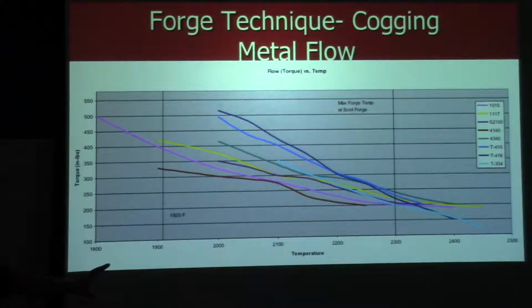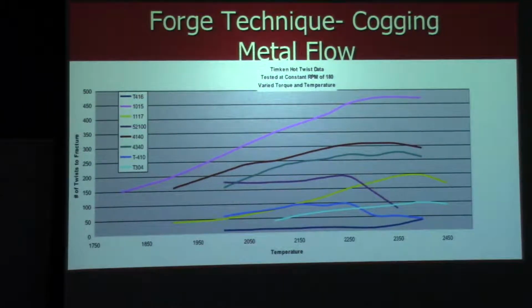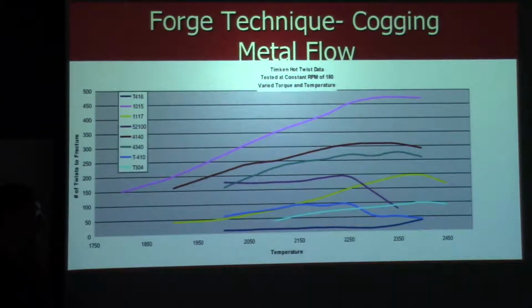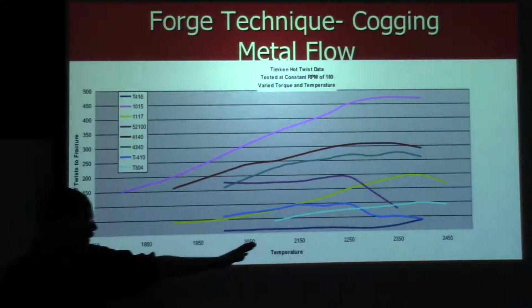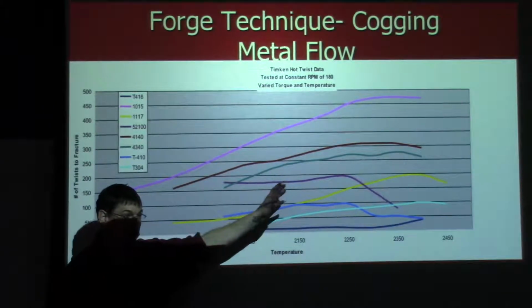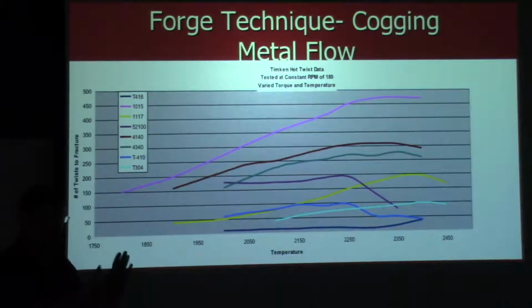Okay, so this is our graph of temperature versus flow stress, or torque as it's presented here. Any other questions? Any other answers to my questions? All right, so we're going to show another graph. This is the other parameter measured from this test, which is the number of twists to failure. It's the same exact situation. Pick a temperature, heat your metal piece up, twist it until it rips in half, and count the number of twists. Then do that over a variety of temperatures, and we can see what happens. On the upper temperature range we have more twists to failure, and at the low temperature range, fewer twists to failure, which gets to where our lower limit comes from, which was the tearing that I was talking about.